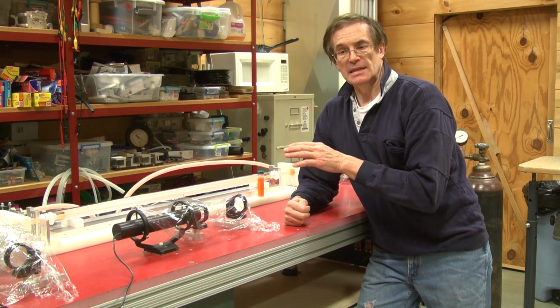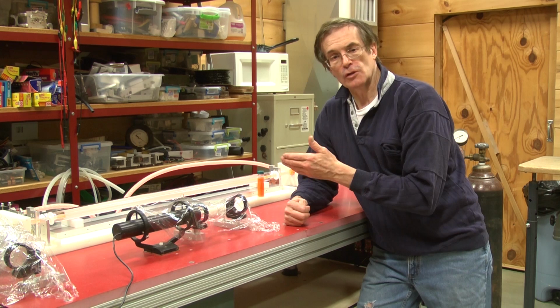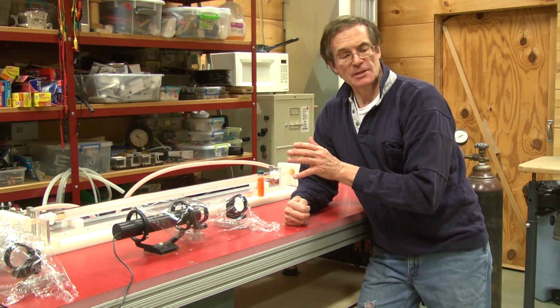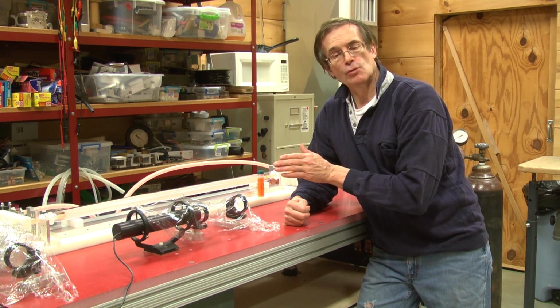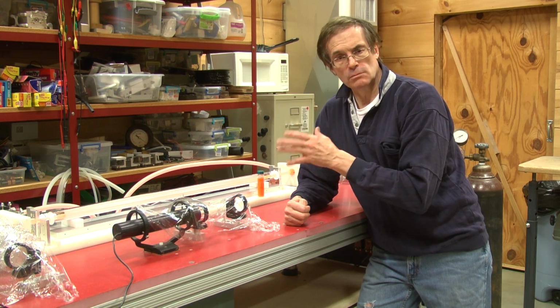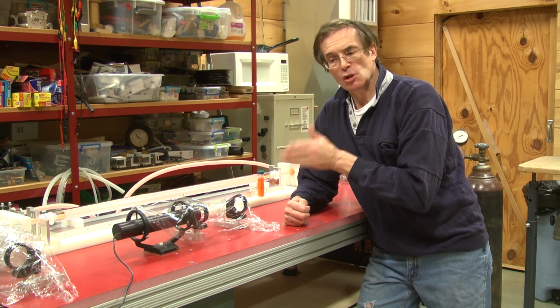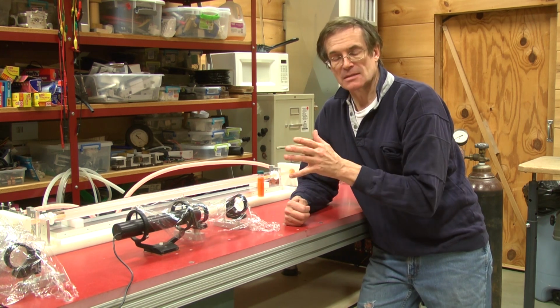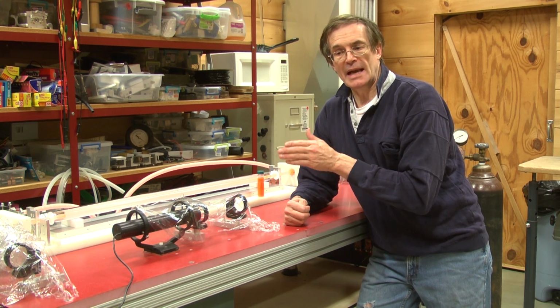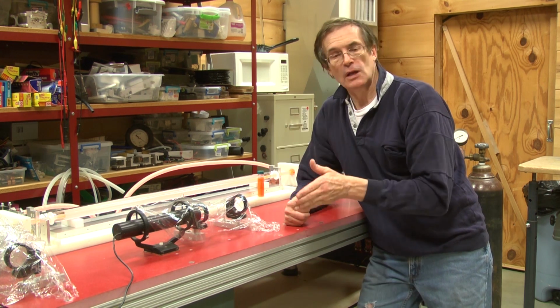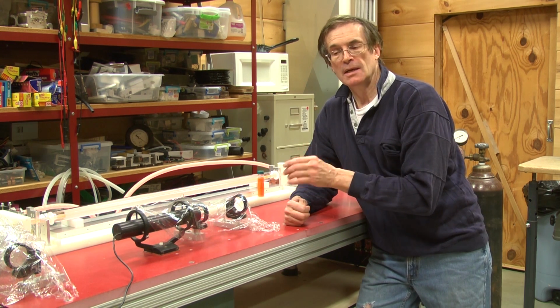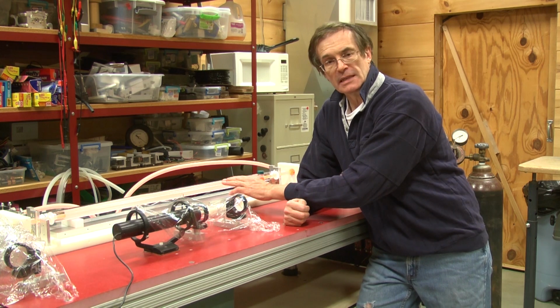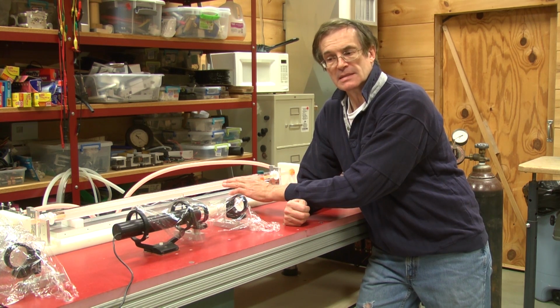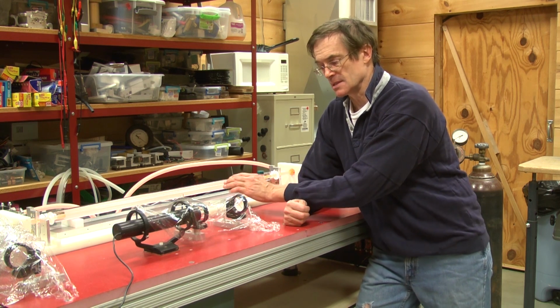And the advantage of having the enhanced aluminum as opposed to, say, just an overcoated aluminum is because some of the coatings, especially the barium sulfate, can corrode the aluminum that's underneath it and darken it and decrease the effective reflectivity. The multi-layer dielectrics that are used to make the enhanced aluminum, those reflective coatings actually provide more protection for the overlying paint white coating that you're going to put on top. The enhancement doesn't really make the reflector in the imaging scenario any better, because the enhancement is somewhat bandwidth limited and it's also angle of incidence limited, so it's not really an advantage over just the aluminum. It's not a way to cheat the original system.